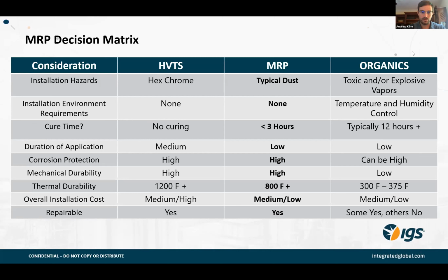HVTS, with many of the chrome alloys used, have high levels of hex chrome, which is a serious concern. We're very good at mitigating it because that's the majority of what we do. That being said, it still can impact your SIMOPS, upstream, downstream, cost of mitigation and things like that. And then on the organic side, oftentimes you're going to see toxic and explosive vapors. And there have been documented cases where people have been hospitalized in SDA applications from an installation with those toxic vapors. So by eliminating those two, that's a significant safety concern and cost mitigation that's taken out with MRP.